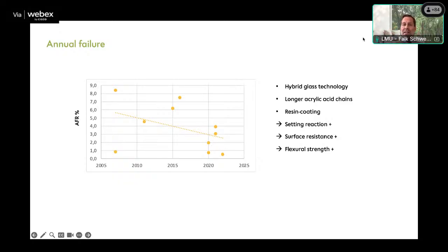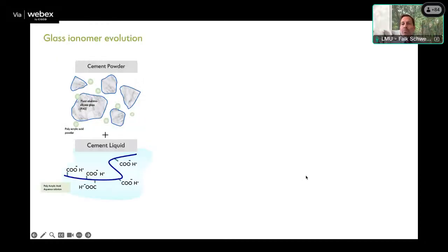I will explain this in a second. And the second reason is that these materials are by now oftentimes covered with a resin coat, which is supposed to increase the setting reaction, to improve it, to make the material more long-lasting, but also to improve surface resistance against erosion, abrasion, so any kind of acidic stuff, and flexural strength, protecting the material against break, fracture. I was asked to briefly introduce that technology here, so I will do this.